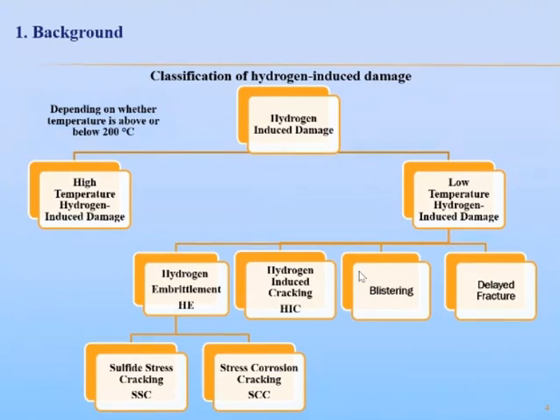Once entered into the metal, atomic hydrogen interacts with the metal structure and may produce damage of various forms, such as hydrogen embrittlement, hydrogen-induced cracking, blistering, delayed fracture, and others. There are also other damage mechanisms induced by hydrogen in metals when hydrogen reacts with metals or with carbon to form hydrides or methane, respectively. Typical hydride forming metals are titanium and zirconium. In this case, hydride causes brittle fracture of the metal along the hydride matrix interface.